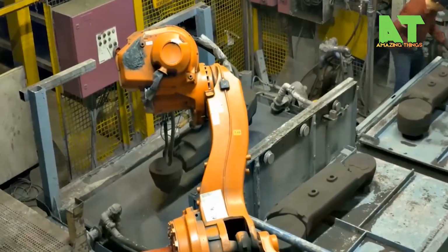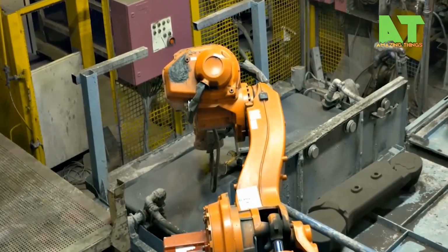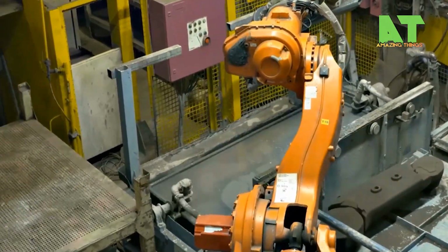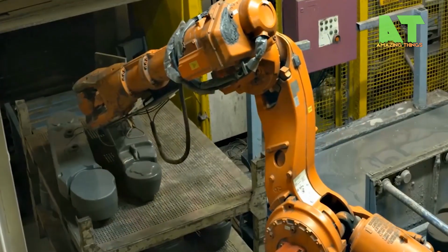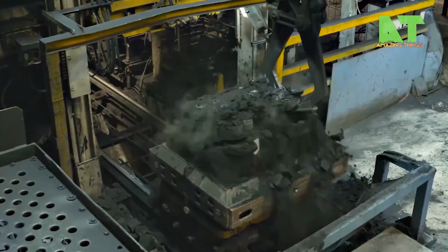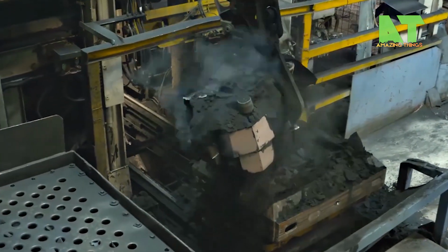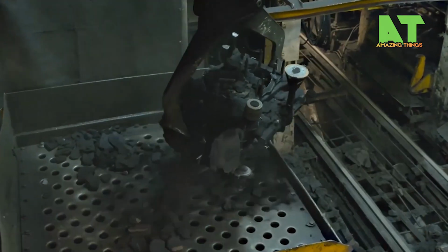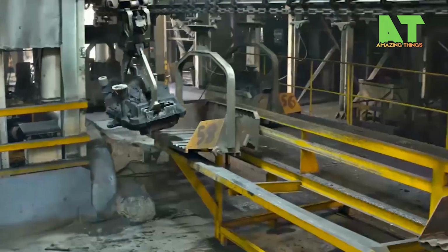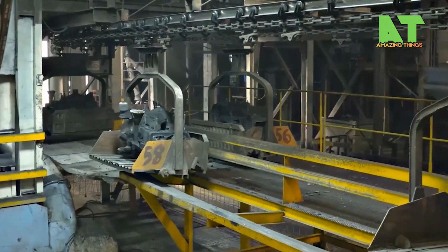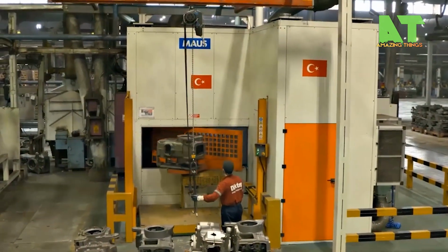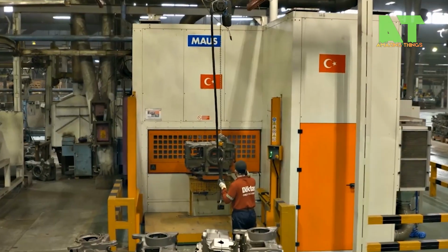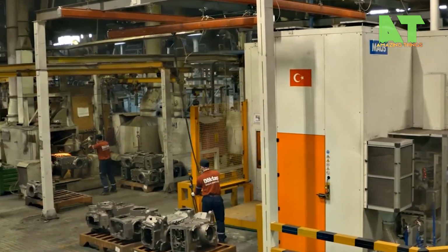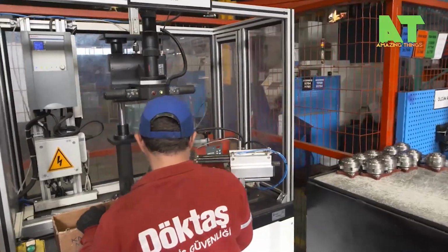load. After cooling, which can take anywhere from several hours to an entire day depending on the size of the part, the sand mold is broken away and the rough casting emerges. It's then shot blasted to remove sand and scale, and sent to the machine shop where CNC milling, boring, and grinding operations bring it to its final dimensions, tolerances sometimes as tight as a few thousandths of an inch. What began as a bucket of sand and a ladle of molten iron has become a precision-engineered component, trusted to protect the heart of a machine working 24 hours a day, year after year.